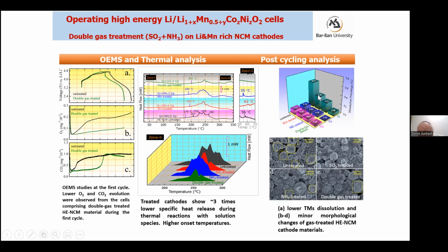So we see, if we compare between double gas treated and all the other samples, single gas treated or untreated, that with the double gas treated we always have much less dissolution of the transition metals, which means that we have better passivation of the negative electrodes.